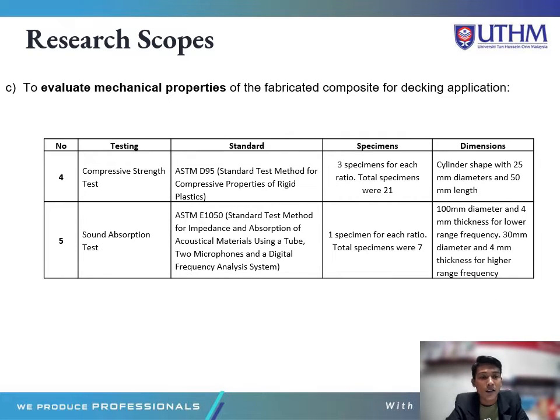The fourth test is the compressive strength test using ASTM D695, with 3 specimens for each ratio, a total of 21, in a cylinder shape with 25 mm diameter and 50 mm length. And the last test for mechanical properties is the sound absorption test using ASTM E1050, with 1 specimen for each ratio, a total of 7. The dimension of the specimen will be 100 mm diameter and 4 mm thickness for the lower frequency range, and 30 mm diameter and 4 mm thickness for the higher frequency range.